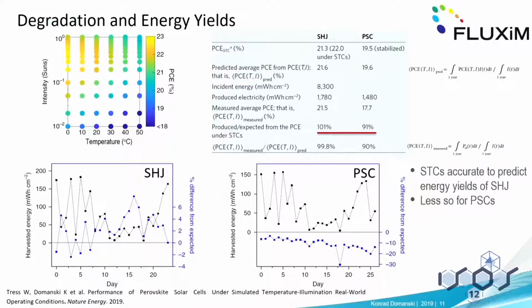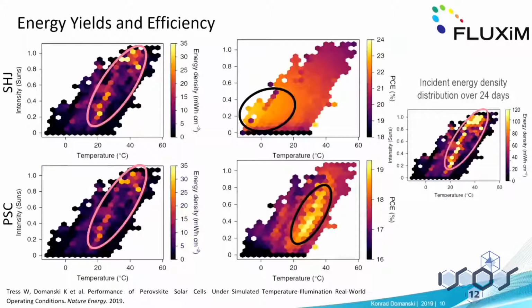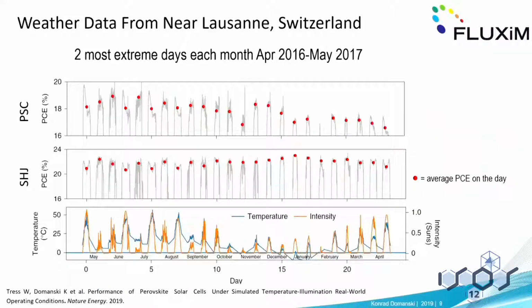And what you actually see in our profile is that we never go beyond 50 degrees. This is the temperature profile. In our data, and this is data from close to Lausanne, 50 degrees is the highest we hit, and -9 I think was the lowest data point in our data set. So for South Europe and Africa, we would make a new study, or a different device architecture. Of course, and if you want to put it on top of Mount Everest, you would need another one again. Yes, with a different range.